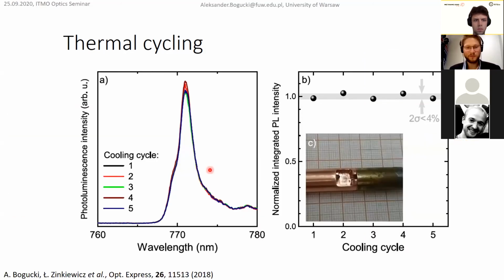And the results of photoluminescence are shown here. So the intensity of photoluminescence on a quantum well, this was an example with a quantum well, is below 2%. Sigma was below 2%. So from that, we concluded that it's not falling off. I mean, it's not detached from the sample. Everything is firmly glued. And what is even nicer, we were storing it on our shelf for about 6 months, and then measured it once again, and everything was fine. So it withstands 6 months easily. We don't know about a longer period, but 6 months was tested.